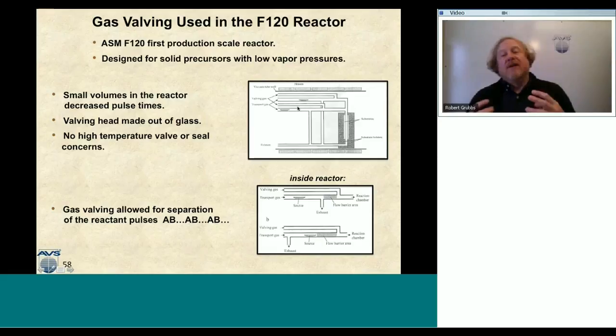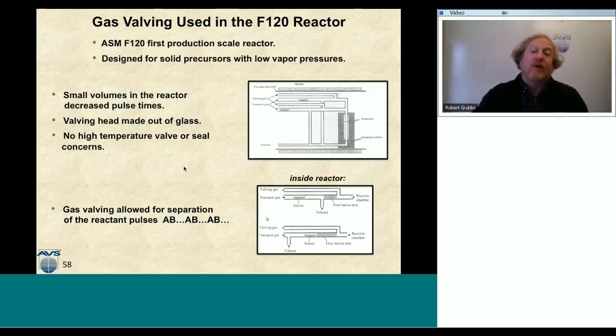because we've had to run this at a very high temperature. None of the valves at the time, there weren't any valves that existed that could actually be heated at a high temperature and still operate properly. So I won't go into much detail on this, but you have this giant glass head that had these drillings into it where you sandwich your precursors, and then you use these exotic gases and these little gas windows I've shown here to keep the precursors isolated while the other precursor was being delivered. So just moving valves around and having flows of gas in certain directions could isolate precursors or enable them to get delivered to the sample chamber. But we needed this gas window to separate the A half reactions from the B reactions. So this worked very well. It was ironic that the first precursor they tried was designed for solid precursors.